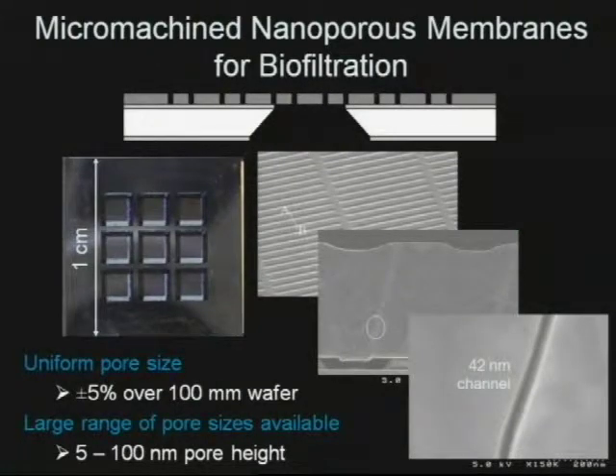We've opted for silicon as a structural material for our nanofilter membranes because of a couple attributes, notably its mechanical durability, its versatility in micromachining, and the ability to use thermal oxidation processes to form very thin spacers that can be configured into very thin pores. I don't have a lot of time to go into the details, but I will highlight this one SEM micrograph here that shows the formation of a 42 nanometer wide channel between two large silicon plates. Here's a cross-sectional view outward, and it shows this is about a 4 to 5 micron thick silicon film, and there are these really thin channels that permeate the thin film. We've actually fabricated pores with critical dimensions as small as 5 nanometers.